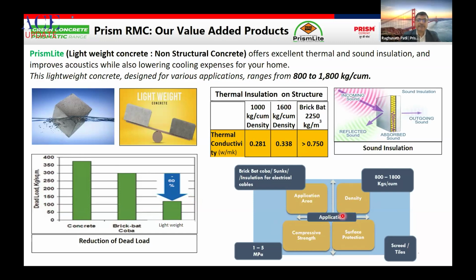So this concrete is used for replacement of brick bat coba, sunken filling, or temporary structures, and the density is 800 to 1800 kg per cubic meter. Here, since the surface strength is very low, surface protection is required. So we need to place a screed or tiles over this concrete. This lightweight concrete, we have done at many job sites and are already supplying in many cities.